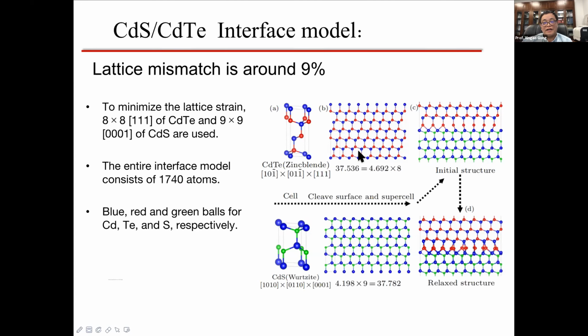We are using 8 unit cells of cadmium telluride on 9 unit cells of cadmium sulfide, and the lattice constants are quite similar. So in this case the lattice mismatch is not that big, and you can put these two things together to form these superlattice interface structures. You can do this with solid structures, but just putting these two things together is of course not that stable.